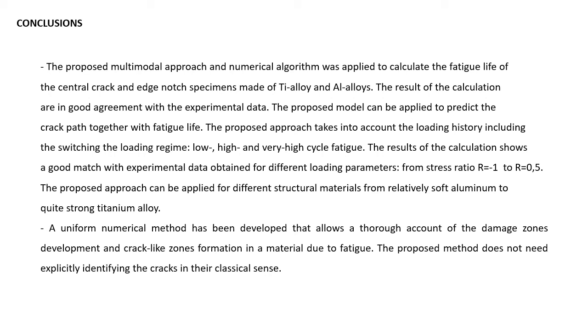The proposed approach takes into account the loading history, including the switch of the loading regime from low, high to very high cycle fatigue range. The results of calculation show a good agreement with experimental data obtained for loading parameters from the stress ratio R -1 to R 0.5. The proposed approach can be applied for different structural materials, from aluminum to quite strong titanium alloys.